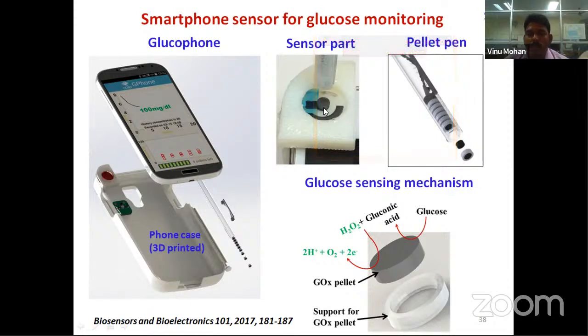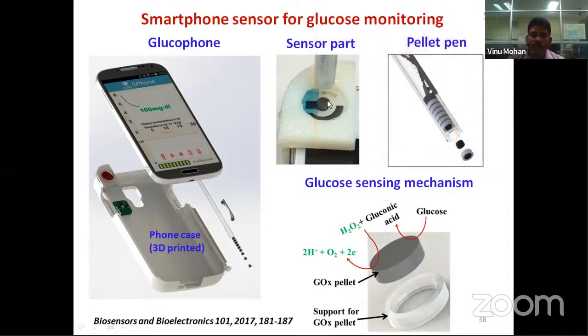And one more thing, under the working electrode, we attached small, tiny magnets. What is the purpose? While preparing this active material, we mixed in some magnetic powders. So whenever we eject one pellet to the area, there is no need to align it due to the presence of the underlying magnet. This glucose pellet, the active layer, will directly go and attach to the transducer, and then we can do the analysis.